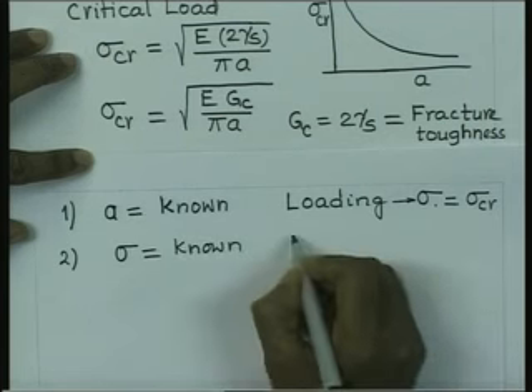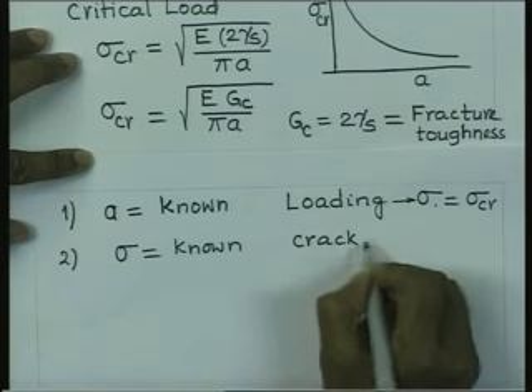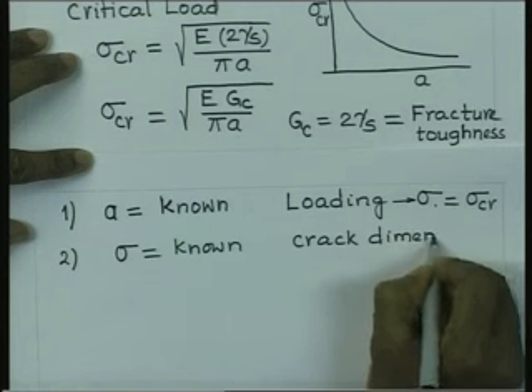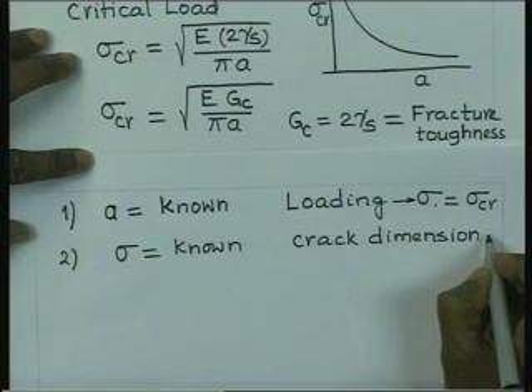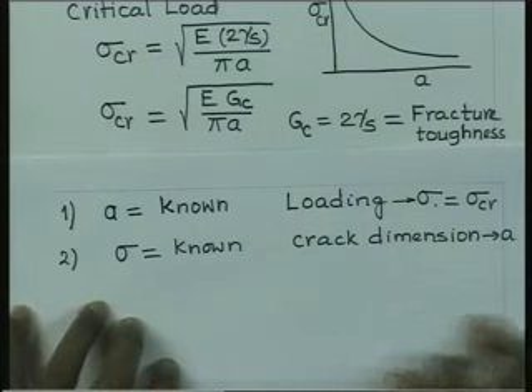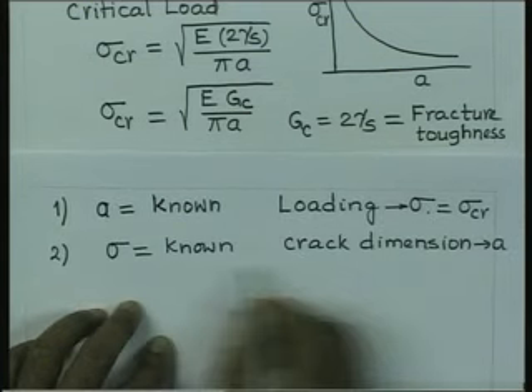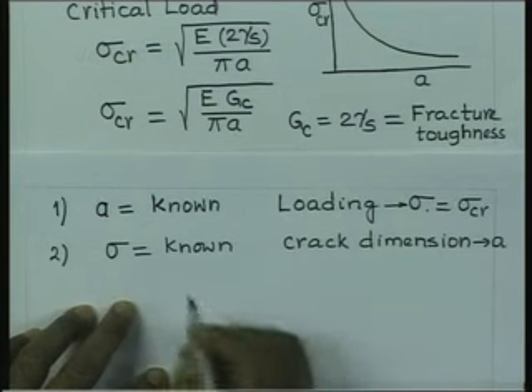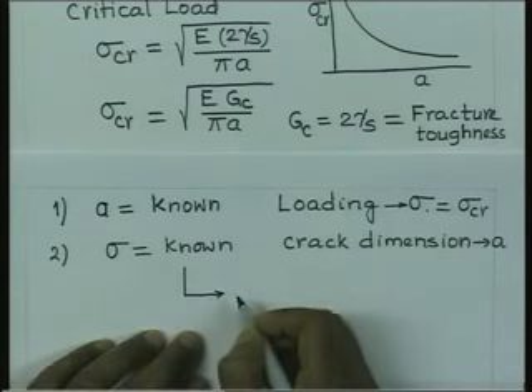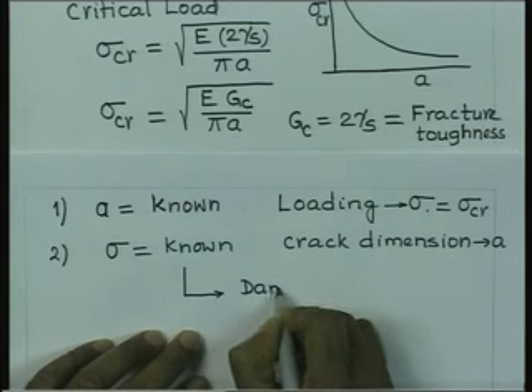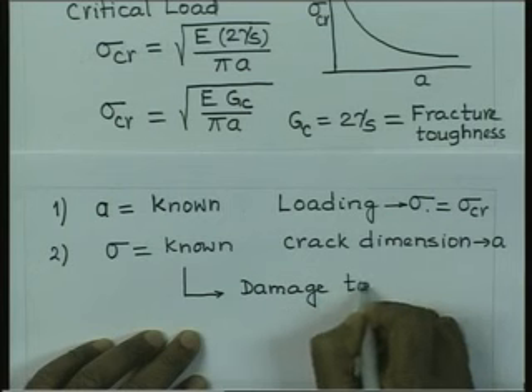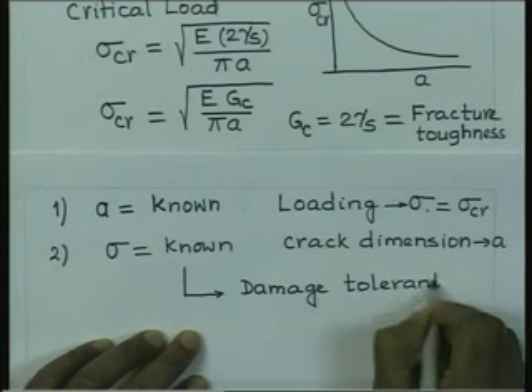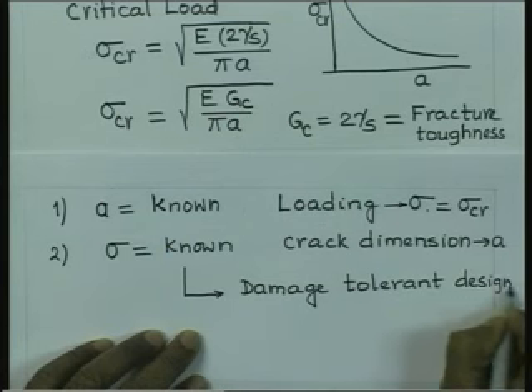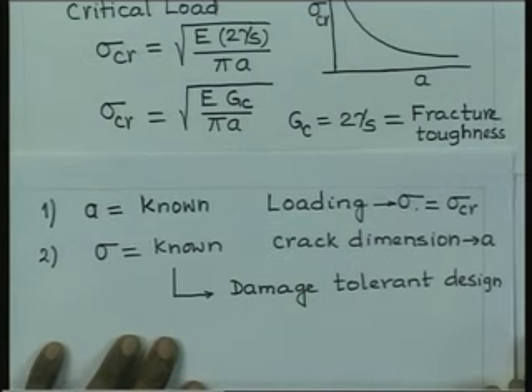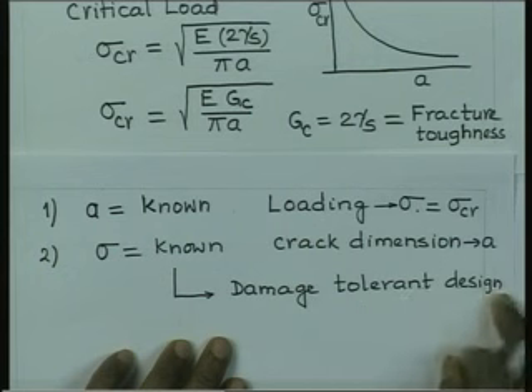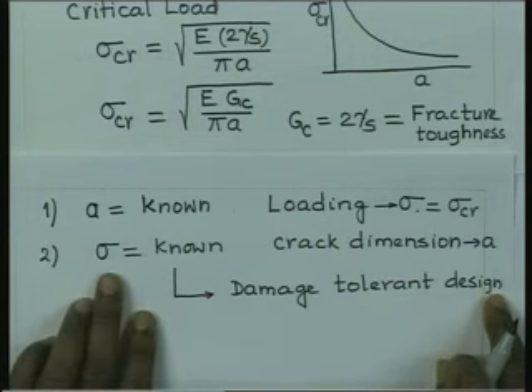Alternatively, if we know the loading on the component, then it is possible to calculate the crack dimension a which will trigger crack extension or failure of the component. This second approach has given rise to a new consideration for design. It is known as damage tolerant design. What it means is that we can calculate how much damage the structure, a component, can tolerate given the loading and the material property.